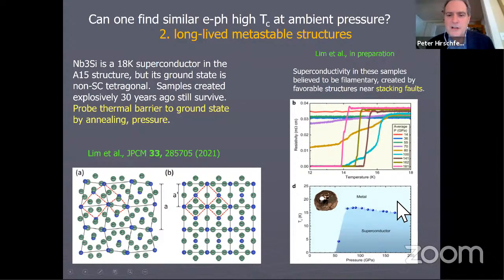Second image, I'm showing you recent results on the creation of superconductivity in a material called tungsten diboride, where we believe that the superconductivity is carried by magnesium diboride-like structures, which are present only in stacking faults, so defect structures which percolate through the material.